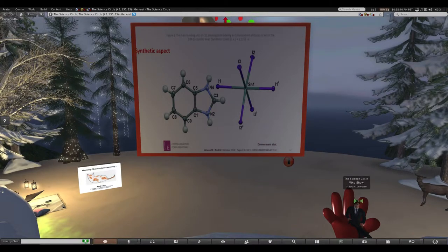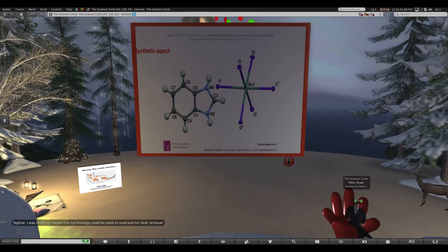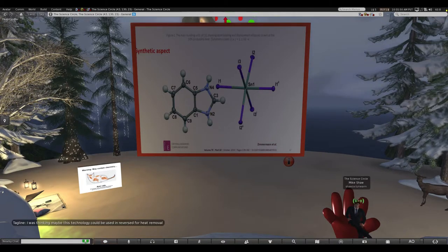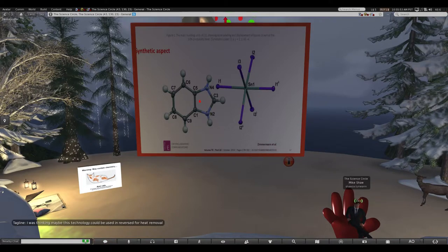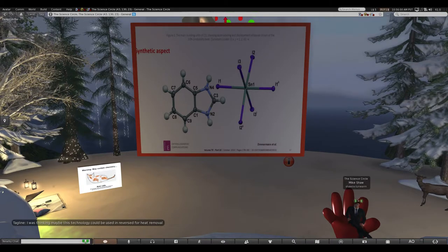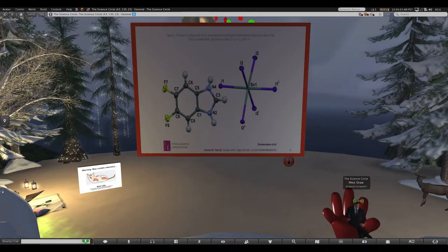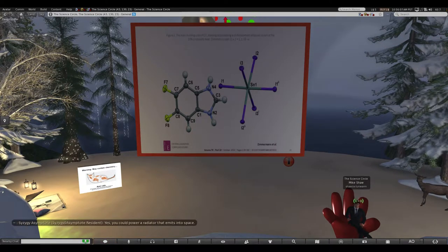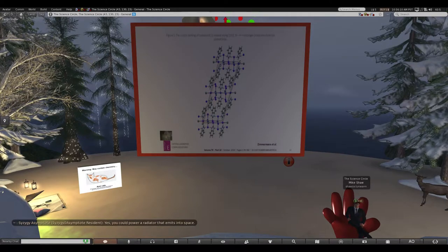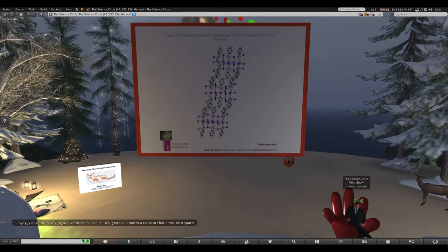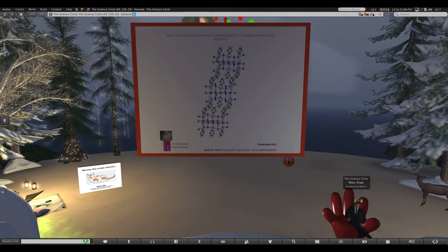So yeah, a couple of slides. This is from a typical paper from recent work where they made the tin iodide. The tin is a little less toxic than the lead, and it does some of the same chemistry. Here you can see they have a different cation. This cation, this thing on the left, would sit within the holes, the cubic holes in the cages. They made a couple of flavors of these things. The second one I'm showing you here is fluorinated. And they have a perovskite structure that's a little bit distorted. This distorted structure actually slows down the movement of electrons a little bit, which is a beneficial thing, and prevents energy wasting recombination of electrons and holes.